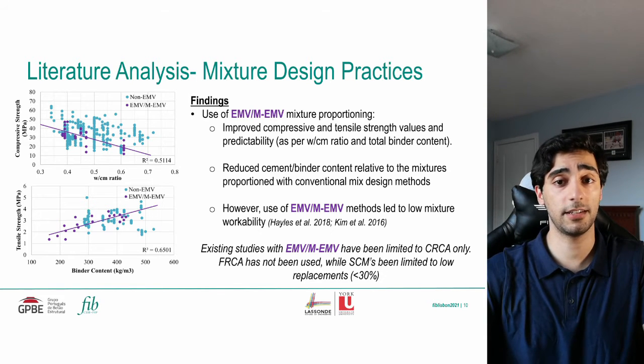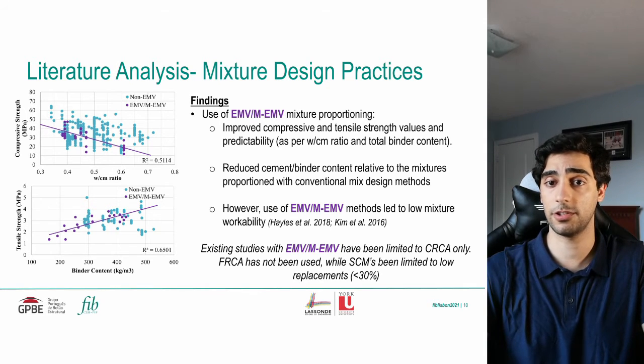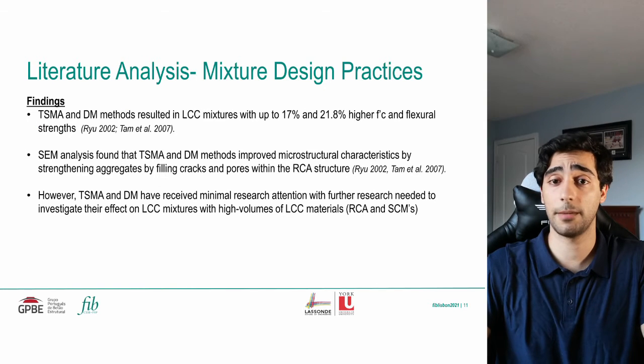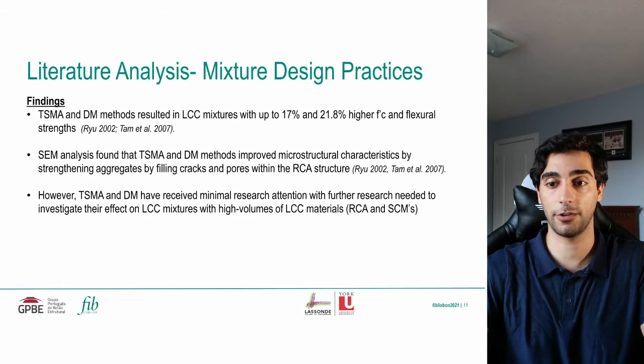It should be noted that the existing studies utilizing the equivalent mortar volume-based mixture proportionings have only been limited to coarse RCA mixtures. The use of fine RCA or SCMs have not been included or have been limited to very small percentages under 30%. In terms of mixing methods, it was found that the two-stage and double mixing methods resulted in up to 17 and 21% higher compressive and flexural strength values, while scanning electron microscope analysis also found that these methods improve the microstructure characteristics, strengthening the aggregates and filling in cracks and voids within the RCA structure.